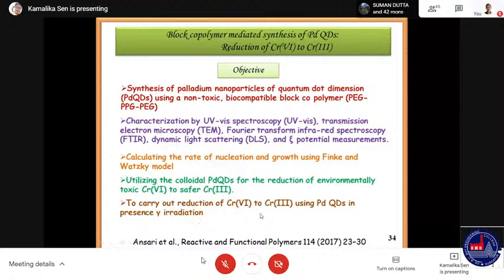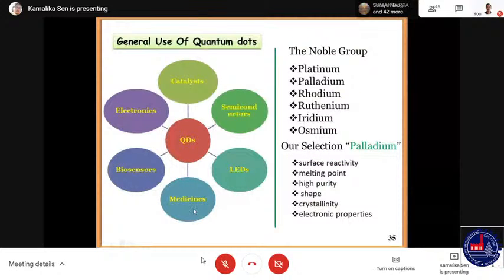and that also in presence of gamma irradiation. So there are many noble group quantum dots reports available in the literature. These are platinum, palladium, rhodium, ruthenium, iridium, osmium, but our selection was palladium because palladium has high surface reactivity, good melting point is high, high purity, shape is almost uniform, and crystalline, they have good crystallinity and they have good electronic properties.